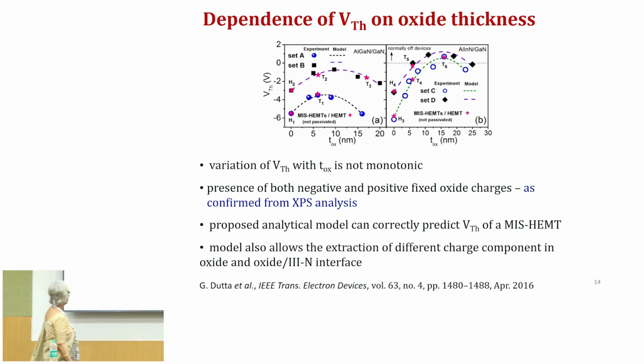Now, interestingly, the point was that the negative fixed oxide charge was really located as a thin sheet of charge at the interface of the oxide and semiconductor, whereas the positive fixed oxide charge was distributed in the gate oxide. Therefore, what was happening is that beyond a certain thickness, it is the positive fixed oxide charge which started to dominate over the negative fixed oxide charge, and that is why you see that the threshold voltage reaches a peak positive value and then it starts to reduce again.